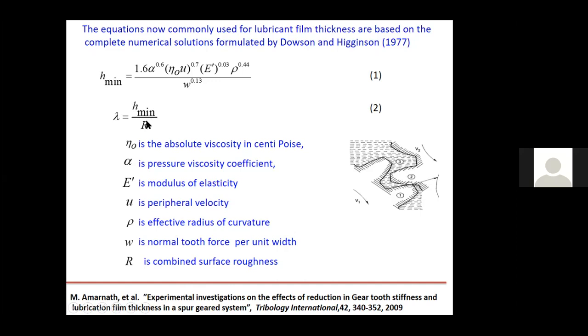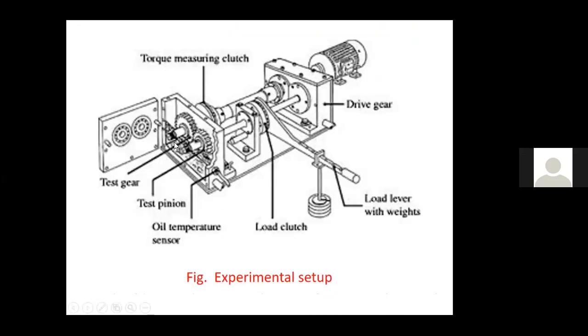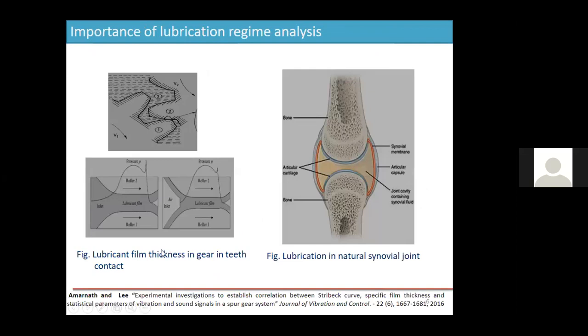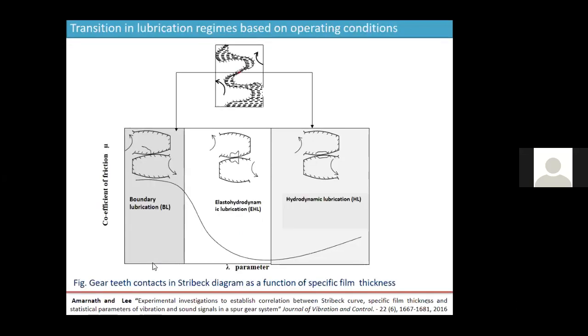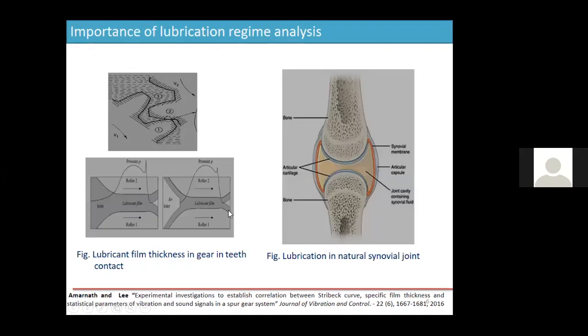If you divide minimum film thickness by combined surface roughness, you will get lambda. Lambda is the specific film thickness. The lambda parameter is used to estimate the lubrication regime in a given machine element. This lambda is the gauging factor for the lubrication regime, whether it is in the hydrodynamic, elasto-hydrodynamic, or boundary lubrication regime.